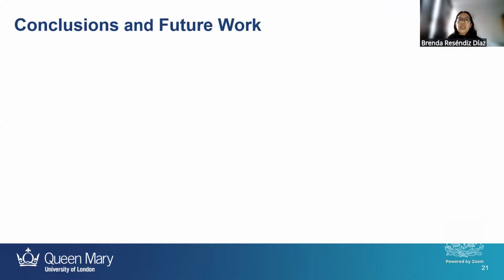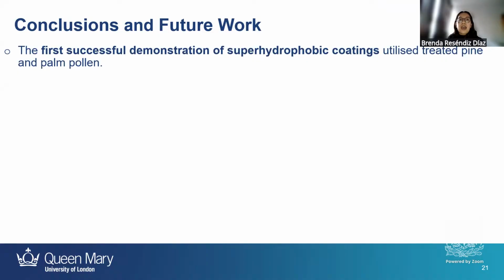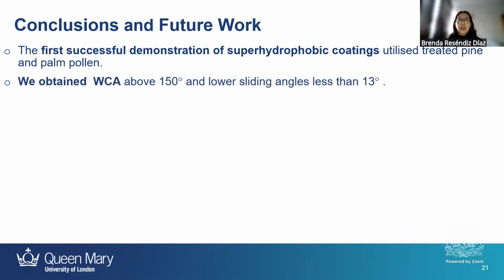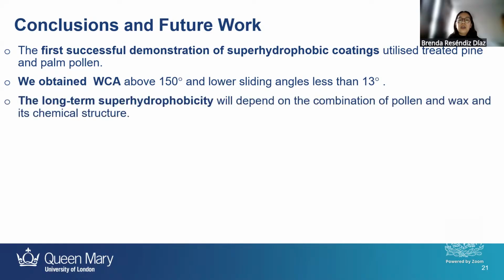For my conclusions and future work, we first successfully demonstrated superhydrophobic coatings using these two specific pollen species, pine and palm pollen. We can obtain water contact angles above 150 degrees and sliding angles less than 13 degrees. Long-term superhydrophobicity will also depend on the system we are using. So we need to know the characteristics of our materials, especially of the waxes, and it will also be dependent on the pollen species.